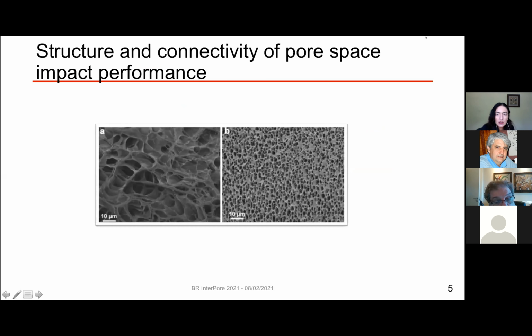The image on the left you see is made with a hydrogel with weak crosslinks. And the result of that is that there is very little connectivity within this material and the pores are poorly defined. The image on the right shows a strong crosslink that was used in this polymer network, and you see very well-defined pores, and this material will have much higher permeability.